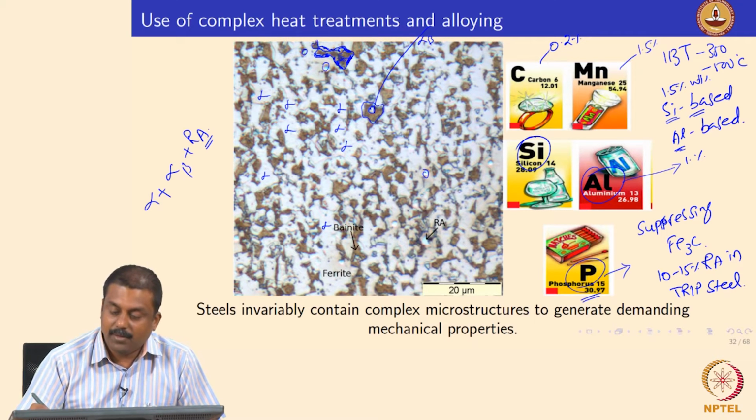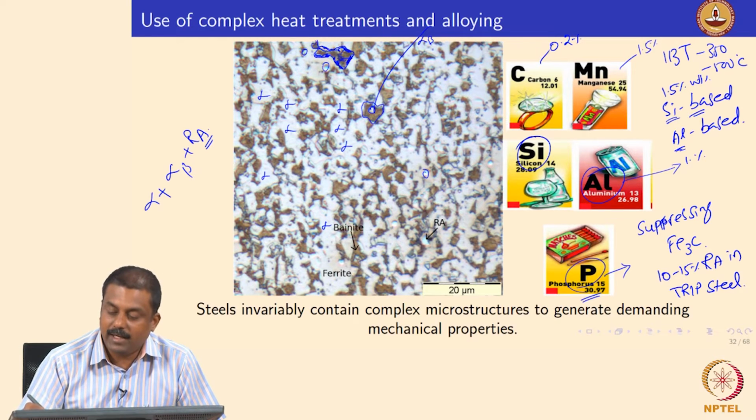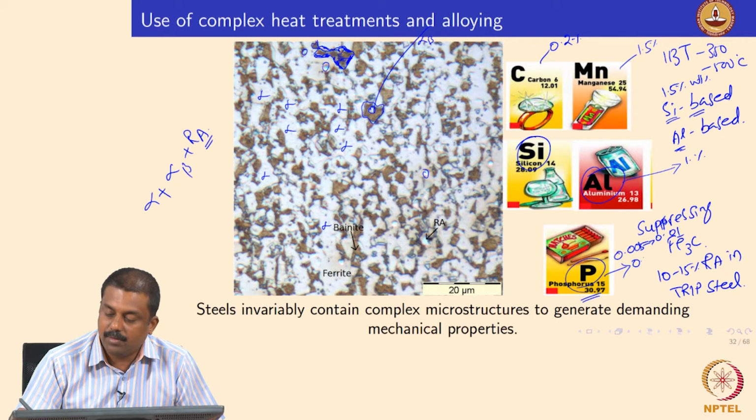But to generate the microstructure in a steel mill, we can increase the phosphorus to 0.005 to 0.01, that's the phosphorus range. But in TRIP steel, to make use of the effectiveness of phosphorus in suppressing cementite and increasing solid solution strengthening, the phosphorus concentration can be increased to, for example, 0.015 to 0.02.